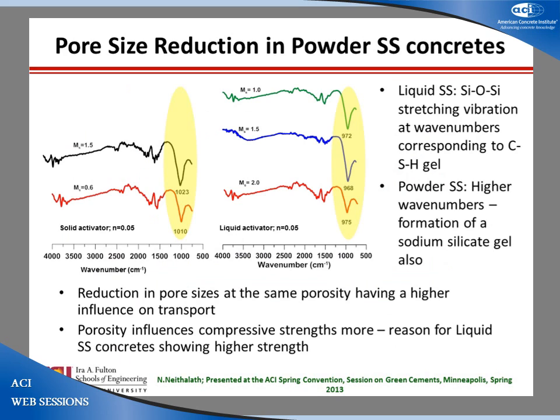So one more reason for the pore size reduction in powdered sodium silicate concretes, and we did a lot of work on that. This is Fourier transform infrared spectra of both the powder and liquid concretes. You can see all the liquid concretes will give you that Si stretching vibration band at about 970 centimeters to the minus 1, characteristic of a lowly polymerized gel, typical of what you see for CSH in cement systems.